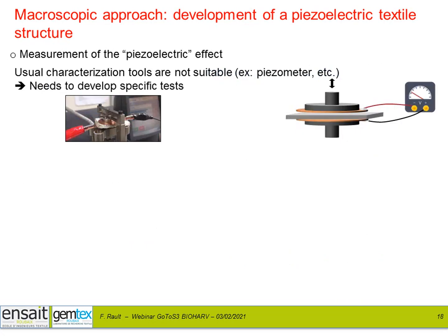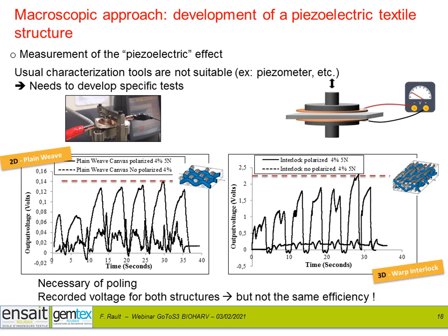The characterization of the piezoelectric effect of textile structures is also a problem to be considered. Indeed, the usual tools, such as piezometer, are not suitable. We have therefore set up a protocol using a DMA coupled to a voltmeter to record the output voltage when our various textile structures are stressed. We conclude that polarization is necessary to optimize the response. The 3D interlock woven structure is 10 times better in terms of voltage than the plane weave. The energy estimated is low, with a value around 1 microwatt per square meter, but this could be improved.